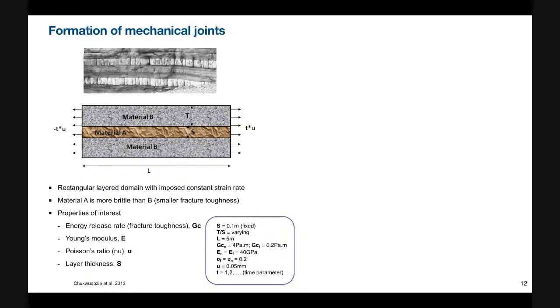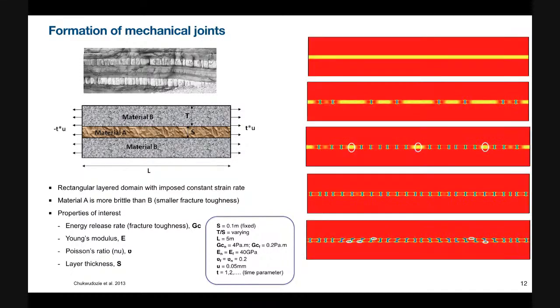And we vary both mechanical properties and geometric parameters, such as the layer thickness of the weak layer. And this is one example of our simulation. So we pull this layer from both sides. In the beginning, damage develops homogeneously, and then this damage starts localizing. Then fractures continuously fill the space between these joints, and at some point it reaches a saturation point. After this saturation point, there are no more new fractures developing.